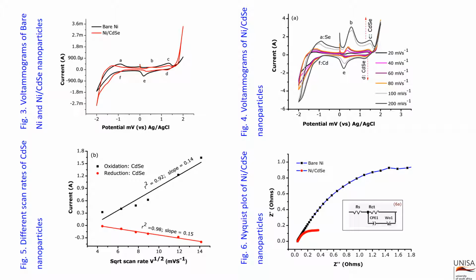In figure 3, compared to the bare electrode, the modified electrode of nickel cadmium selenide revealed several redox complexes at the electrode interfaces in figures 3 and 4. In figure 4, the cadmium selenide nanoparticles showed two redox complexes at an oxidation peak potential of 1.33 volt and a reduction peak potential of 1.28 volt respectively, as shown in figure 4 C and D region.